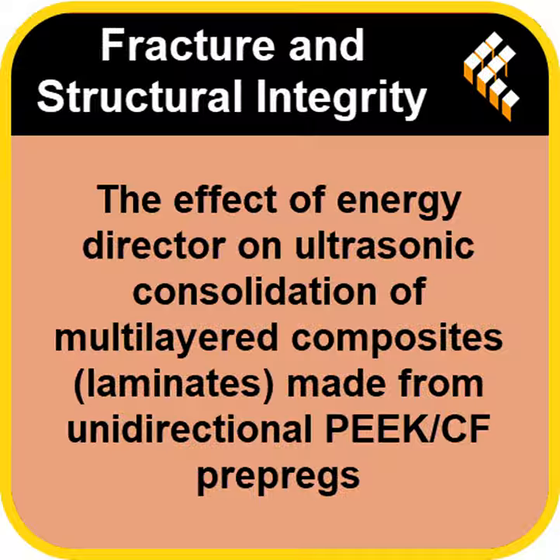Okay, so when the layers melt, the material squeezes out, so you'd expect it to get thinner. You would. And for the samples with the energy directors, the thinning was pretty linear. More time meant more melting, more thinning. Simple. At 1200 milliseconds, they saw a good amount of thinning. But the results without the energy director were completely different. Totally different. They followed a distinct S-shaped pattern.